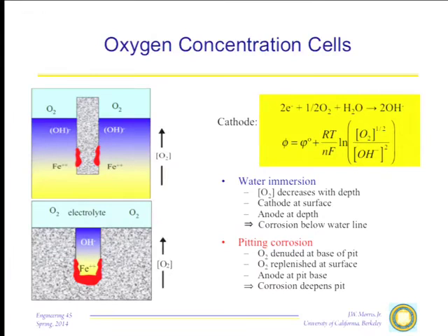If you go down to the bay, just off of 80, where the bay is kind of shallow just before you get to the bridge, for reasons that I do not know, there are a number of iron poles sticking out of the water down there. If you were to go look at those iron poles, you would find corrosion. And the interesting thing you would notice about that corrosion is it's not right at the waterline. The corrosion is always maximum a bit below the waterline. The waterline is up here, the corrosion is worse down there.